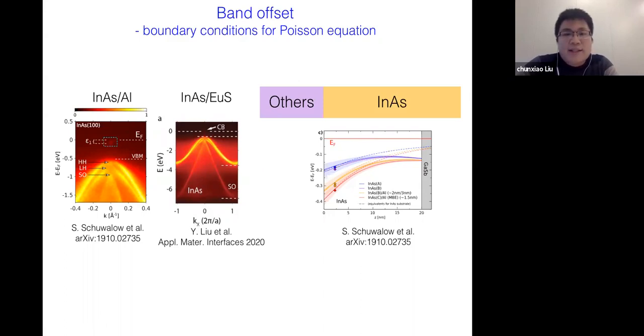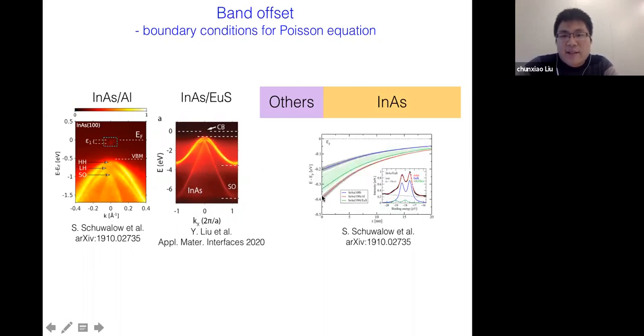So we extracted the band offset value and the band bending effect for europium sulfide in this work. It turns out that, as shown by the green line, the band offset value between indium arsenide and europium sulfide is in between aluminum and vacuum. That means the electron accumulation at the europium sulfide interface is enhanced relative to the bare indium arsenide surface. So this is the first central result of our work, the value of the indium arsenide-europium sulfide band offset. In the following work, we will use this band offset between indium arsenide and other materials as a fixed value in solving the electrostatic potential self-consistently. Okay, so this summarizes the first part, the method part of this work.